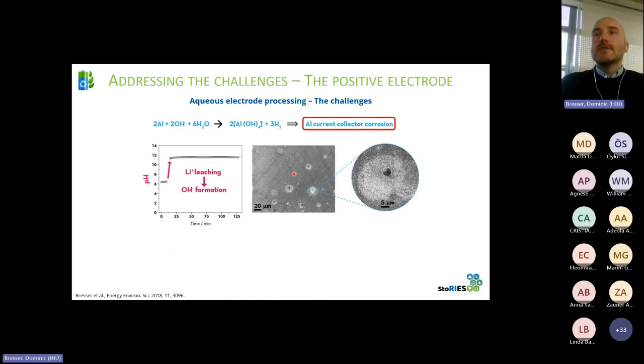But there's a reason why it's not done yet, and this is that all these NMC type lithium transition metal oxides are very sensitive towards water. As soon as they get in contact with water, you observe lithium leaching out of the structure of the cathode material, which in the presence of water results in hydroxide formation. These hydroxide anions then tend to attack the aluminum current collector that is used for the positive electrode, leading, as depicted here, to pitting corrosion. And that's a big issue.